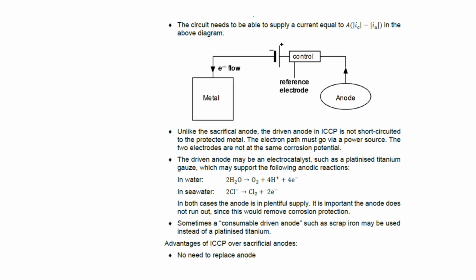Alternatively, we might not want to just use the electrolysis of the nearby water to provide the driven anode. We could instead use a consumable driven anode. This is fairly common. We might have a load of scrap iron, some sort of iron that's been condemned. We could simply strap that to the driven anode connection of our ICCP system, and the driven anode is forced by the applied current to undergo an anode process, and that's probably going to be the dissolution of the scrap iron. But that's okay, because we don't really care about the scrap iron.